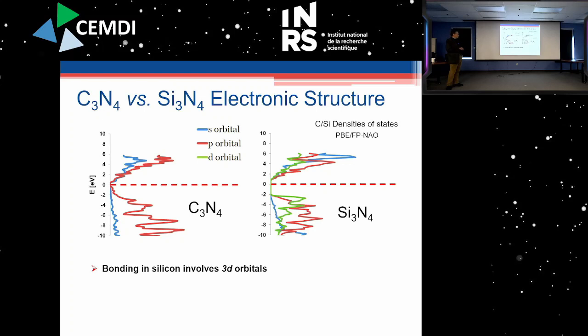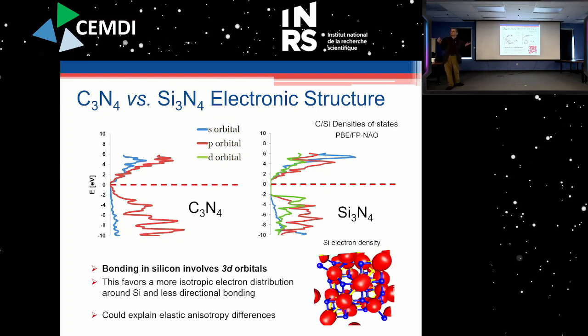And so when you look at the densities of states for a material like carbon nitride, and here we projected them as an SPD contribution, of course you see that for carbon nitride, there is absolutely no contribution of the d orbitals in there. They're way too high in energy to be accessible, even upon favorable interaction with bonding nitrogens. However, for silicon nitride, the silicon d states, which are normally unoccupied in most situations, acquire significant population, as you can see here in green. These are the d orbitals, or the d states. So bonding in silicon involves the 3d orbitals. Completely different from the gas phase picture, of course, where these 3d states are not available for silicon, right? So it's a purely condensed phase occurrence.